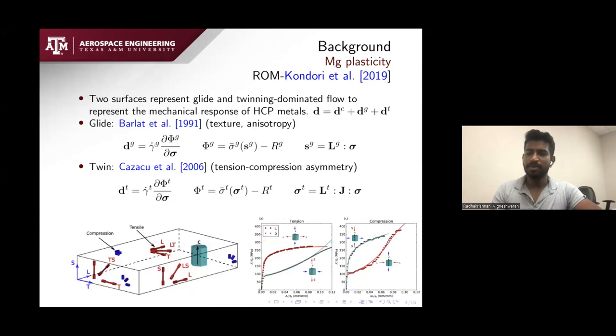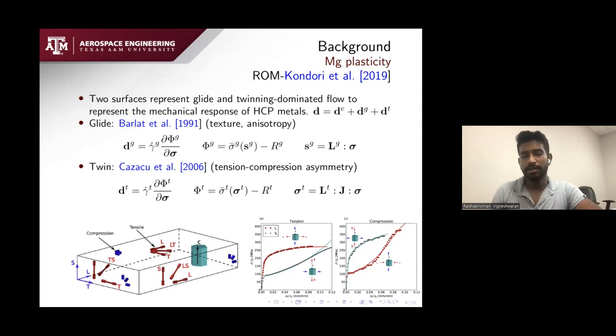A second example for magnesium plasticity is by Kondori et al., who used a reduced order model to represent glide and twinning deformation modes in magnesium plasticity. Although these kinds of models lose fidelity in comparison to crystal plasticity models, they are more practical for structural simulations because combining magnesium plasticity and voids is computationally too expensive. Even with reduced order models, you get all the essential deformation mechanisms: glide, twin, tension-compression asymmetry, and anisotropy.